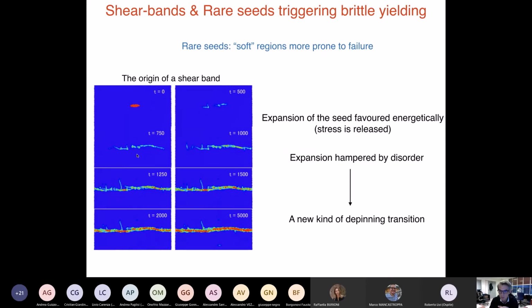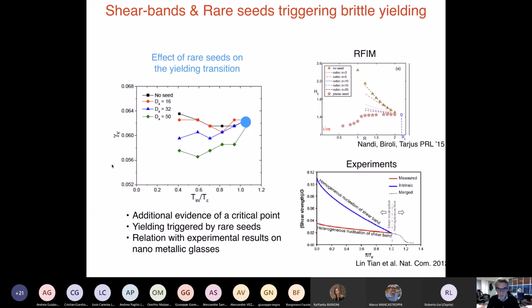So the brittle yielding, the discontinuous yielding, is related to a depinning transition of rare seeds, and these rare seeds are low-dimensional objects: a shear band, or in 3 dimensions a shear line in 1 dimension. And we can do exactly what we did in the random field Ising model to make this idea more concrete. If you remember, if the transition is due to the rare seeds, it means that there are super big finite size effects. So the way to see that these seeds are really relevant is that even if the system is not very big, you can put them by hand. You can put one seed that you would need a super big system to have, and then you see how the existence of the seed affects the transition, and in particular whether the critical value of the deformation changes.